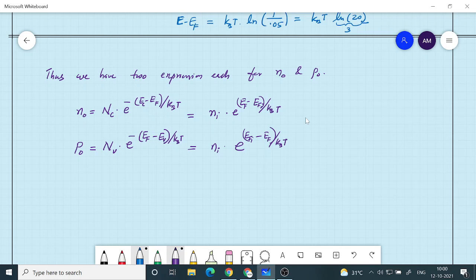For an intrinsic material, what is the carrier concentration? That is going to change if EF is going to go above EFI. You can see from these two equations that if EF is above EFI, what will happen? Then we have N0 going to be greater than P0. Why? Because N0 will increase, it will be Ni into e raised to (EF minus EFI) by kBT. This is going to be a number much larger than 1. So N0 will increase, whereas this is going to be lesser than 1 because EF is above EFI. So EFI minus EF is going to be negative, so this is going to be a quantity less than 1. So P0 will reduce.